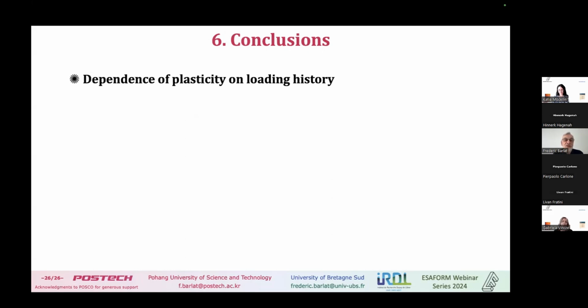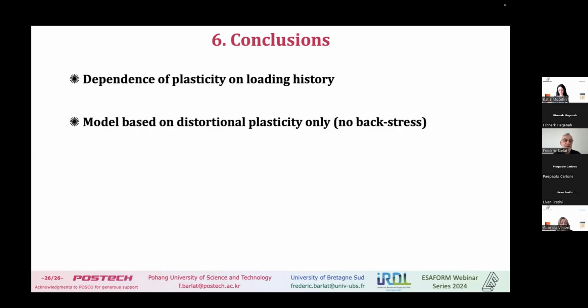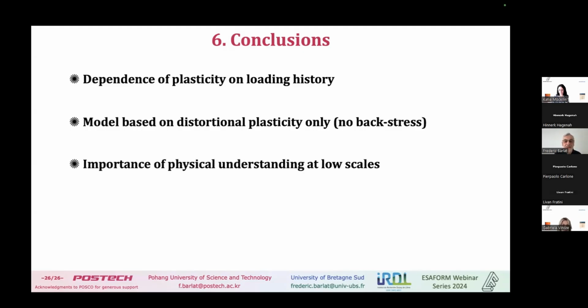So the conclusion: we observe that there is a dependence of plasticity on the loading history, and with a model based on distortional plasticity only, without back stress, we are able to represent the behavior quite well. I showed you several aspects of the microstructure, like the texture or dislocations and so on. So physical understanding is important to develop the model at a continuum scale.